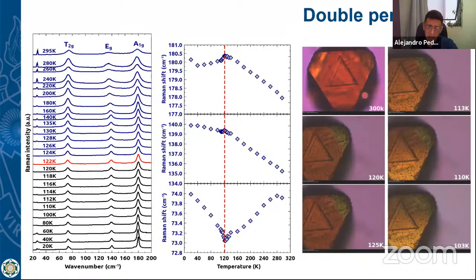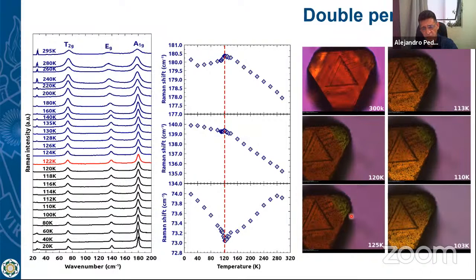And if we take a look at how the birefringence of the crystal changes as a function of the temperature, we really see, between around 120 Kelvin, a change in the color of the crystal. Or let's say it's a change in the birefringence, because we are looking at the crystal between crossed polarizers, and which is associated to the phase transition.